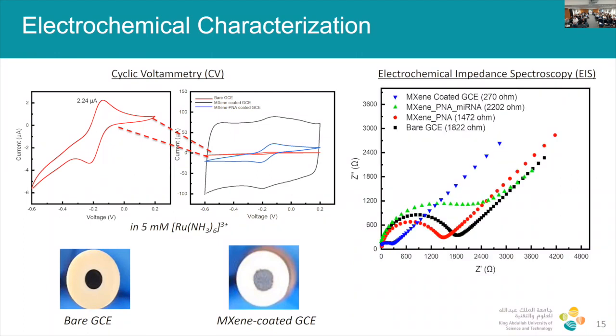We confirmed these results with electrochemical impedance spectroscopy. Really, here for the non-electrochemist, what you want to see is that electrochemical impedance spectroscopy basically tells us the charge transfer resistance at the electrode surface, right? And so how is that characterized? It's just the radius of these semicircles. So the greater the radius, the greater the charge transfer resistance. So you'll see something really fun here. If we have our bare glassy carbon electrode, the charge transfer resistance is about 1.8 kilo ohms.